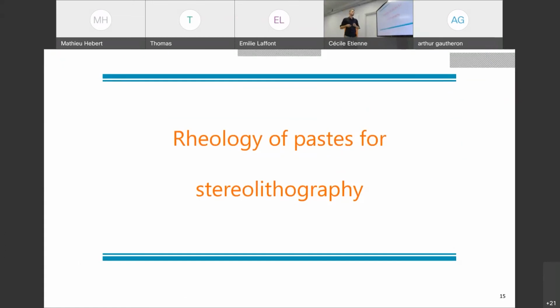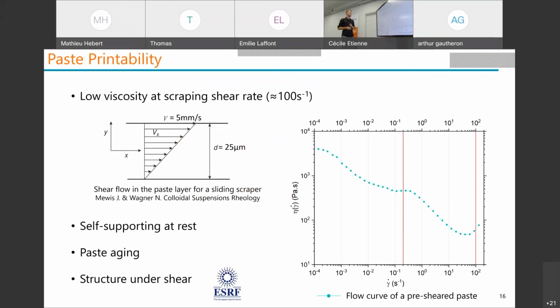And I want also to tell you a bit about the rheology work I have begun. Why is rheology of the paste important? Because to make sure I have a very regular surface before polymerization, when I have my scraper blade, I need a low viscosity. So it would fill every void and be very regular. I have calculated that we are at a big scraping shear rate, so it's low viscosity at high shear rate, but I also need high viscosity at rest. Actually, I need it to be self-supporting. So when I don't scrape, I don't want my paste to fall around.